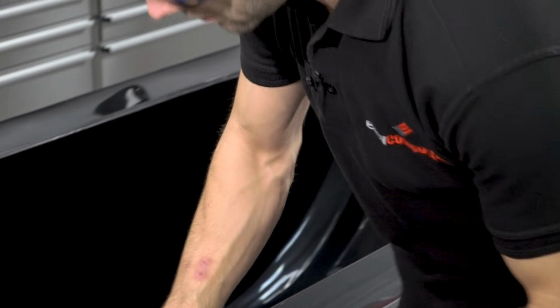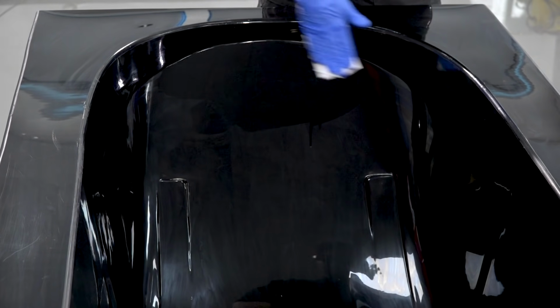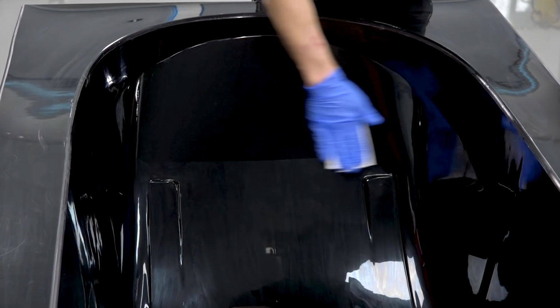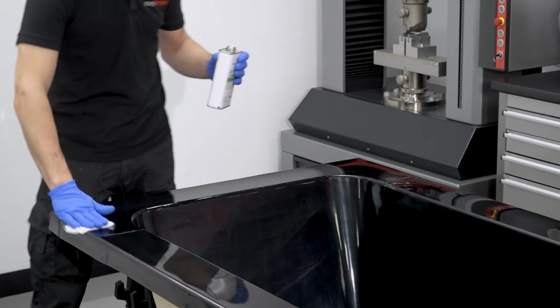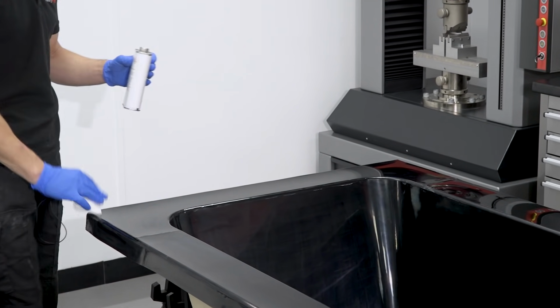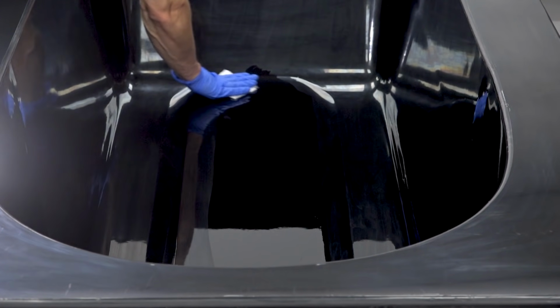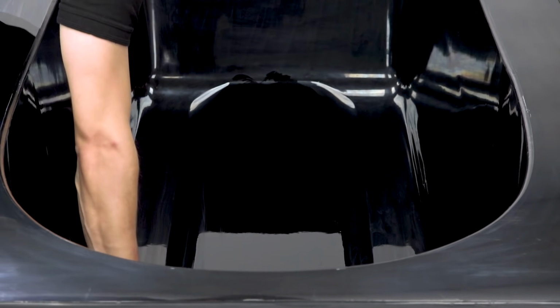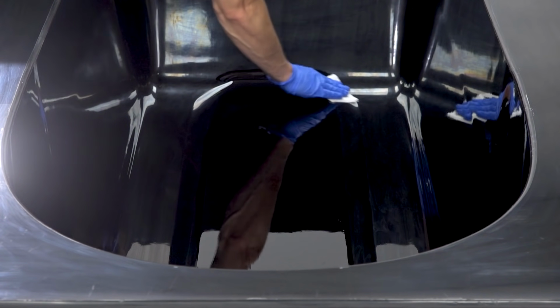As with all composites projects, we need to start with the release agent, which is a chemical coating that will stop the resin of the part adhering to the mould. In this case, we're applying 6 coats of Easy release agent. You will see us using this release agent in most of our other videos. The application method is to wipe a thin film systematically over the surface. On a new mould like this, 6 coats will be applied. After this, only 1 coat between releases is required.